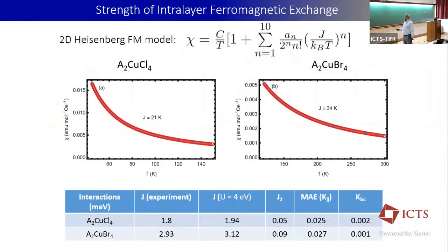And to estimate the J, because these are 2D Heisenberg systems and these are well studied, you can use the expansion method to estimate it from the susceptibility. The first term is basically your Curie term, but you can include these expansion terms here, and you can calculate the J. These are the fittings for two compounds. In one case we get J 21 and in the other 34.